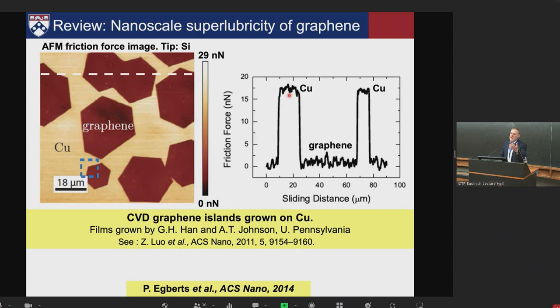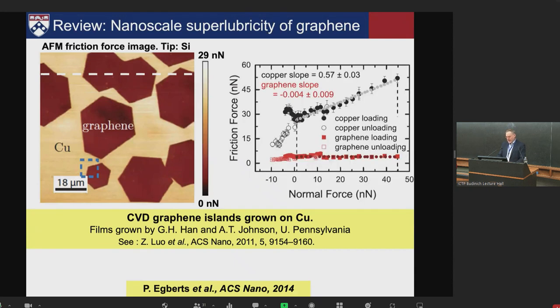It's really, there's some oxide on the surface. So oxide surface, high friction; graphene, extremely low, in the limit of what this AFM can detect, a couple nanonewtons of force. So this is impressive. A single layer of carbon atoms interposed between a tip and a substrate is all you need to reduce friction by an order of magnitude or better. And not only that, this is quite robust over different loads.